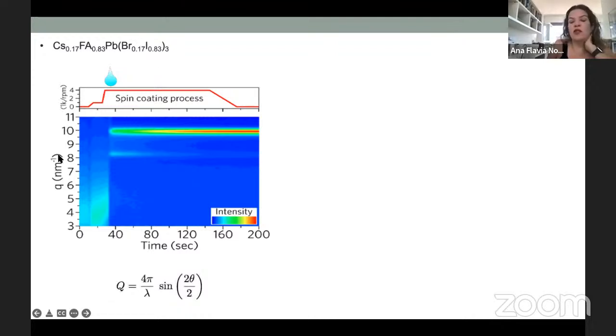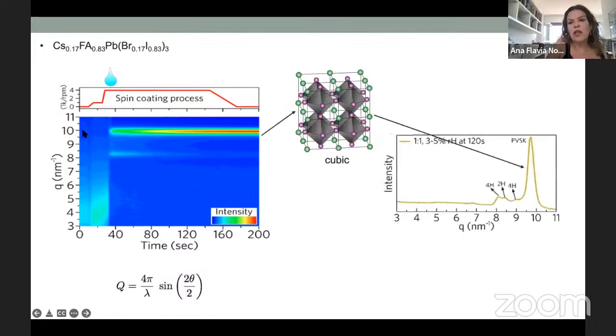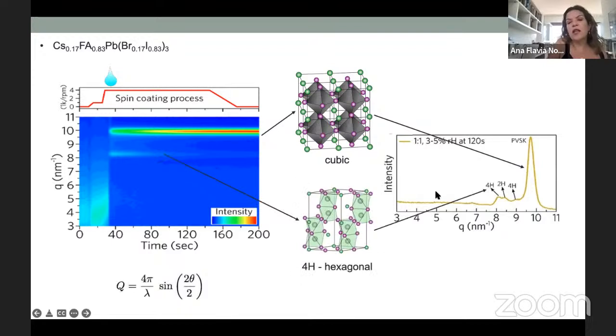So this is the data that you can get when you go to the synchrotron, where you can perform in situ experiments. You can plot the Q. Remember that Q is related to theta. You can plot Q as a function of time. So this is what we have here. In the beginning of the spin coating, when I just drop the precursor solution, we have this blurry signal here. And then when you drop the antisolvent, you start to see the formation of the perovskite, this peak here, Q equal to 10 nanometers minus one, is the peak of the cubic perovskite. But also, as you can see here, we have some peaks below 10 that correspond to the hexagonal phases.